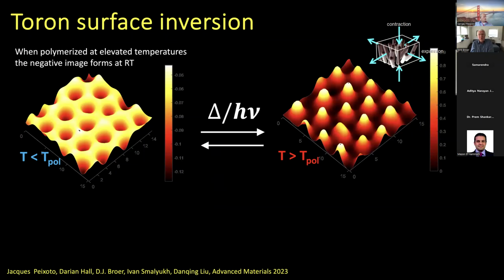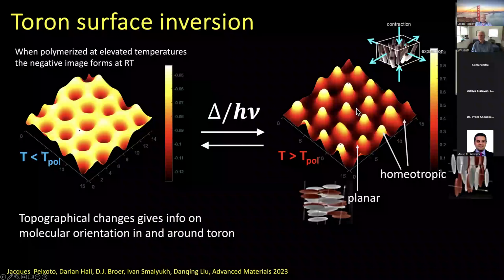And you can also play with the inversion again. If you polymerize it at a somewhat higher temperature, then that temperature gives the flat state. If you cool down, you will have just the inverse of the heating. Then the planar area starts to shrink, and the perpendicular area starts to expand. And then by heating, if you go through this temperature of polymerization, then the opposite will occur.